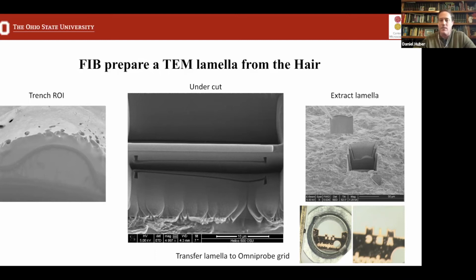Then you're going to back tilt the sample and use the ion beam to cut out the sides and underneath of the specimen. If you see in the picture on the right hand side, there's a micro manipulator needle that we're going to use to pick up the lamella and transfer it onto a little Omni probe grid. That's what we're going to use with our tweezers to pick up and transfer the specimen into the TEM holder. It's in the lower right hand corner.